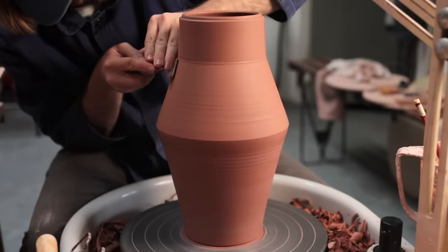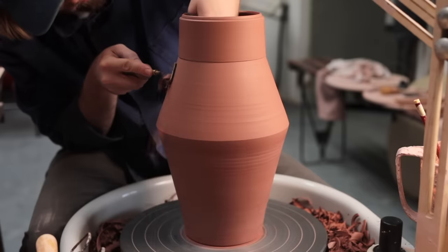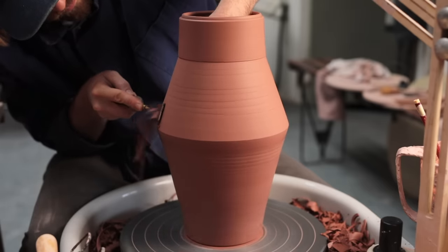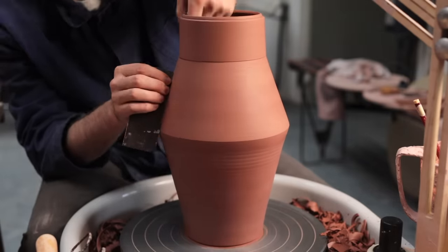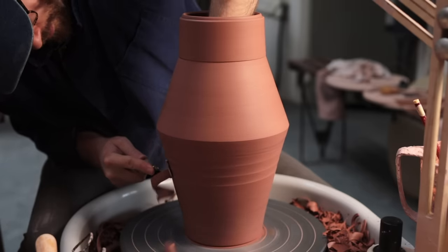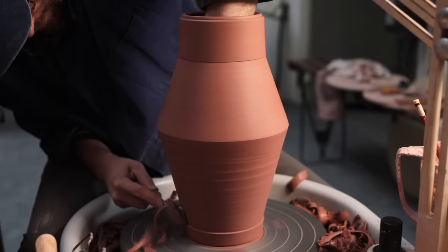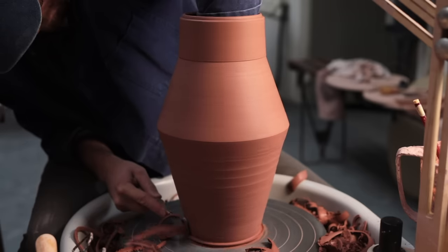As my aim is to make a pot with straight planes, I use tools with straight blades — not only is it easier to turn a straight line, but I can use this straight piece of metal like a guide to see if the part of the pot I'm turning is actually flat. Typically, when I remove mass from a pot, I use one of these very sharp tungsten carbide turning tools, but they don't leave the nicest surface and often they can chatter, leaving a slightly uneven finish. So once the majority of the weight has been removed and the shape is roughly where I want it, I burnish over the surface with a straight metal scraper that's slightly flexible, and due to its length I can use it like a guide to make sure each plane is perfectly flat.